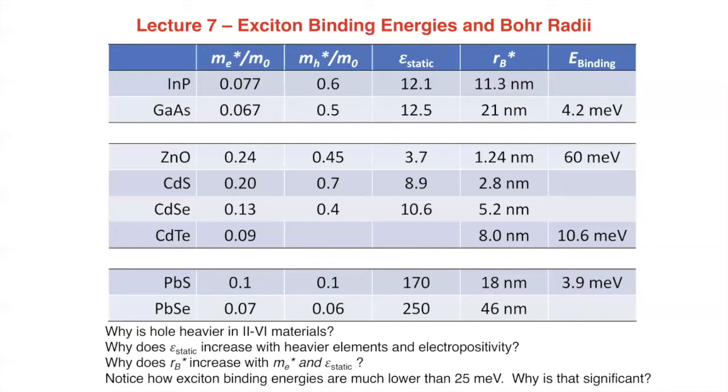and so you get big orbital overlap and big bandwidths for s orbitals. And so the conduction bands in all of these materials have big bandwidths, and that gives rise to these small effective masses, right? A big bandwidth is going to have high curvature, low effective mass, big delocalization. Holes, weaker delocalization, and because they have this higher effective mass, that's because the bonding is not as good.